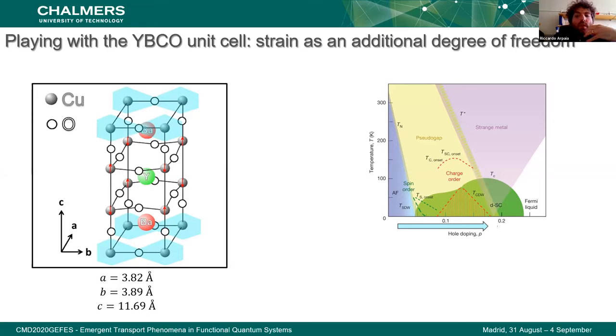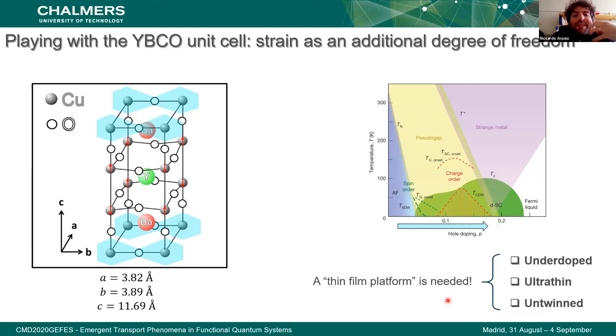So to study YBCO thin films, first of all, underdoped films of high quality are needed. But of course, that's not enough because what we need to have is a proper thin film platform. Indeed, we also need to grow high quality films as a function of the thickness down to a few unit cells, so that the strain effect induced by the substrate can be enhanced. And finally, the films have to be also untwinned, since we want to avoid a random rotation of the unit cell, so as to preserve basically the unidirectionality of the copper oxide chains throughout the whole sample. And basically, this platform is what we have developed at Chalmers during the last decade.